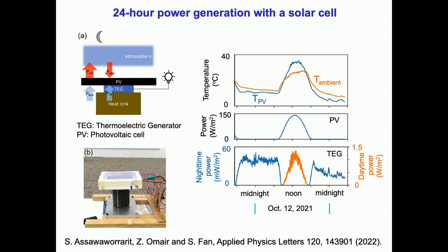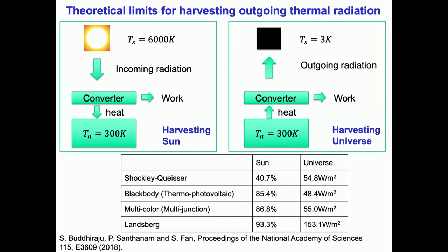But for these things, it's important to understand what the fundamental thermodynamic limit would be. And so, as it turned out, for every technology associated with harvesting sunlight, there's a symmetry that maps into a technology that harvests the coldness of the universe. And therefore, for every theoretical limit for solar energy conversion, you can compute a corresponding power density limit for harvesting the energy from the universe. And the theoretical number actually is quite substantial. These are electricity numbers. They range from on the order of 50 watts per meter squared all the way to about 150 watts per meter squared, depending on the detailed scheme that you consider.